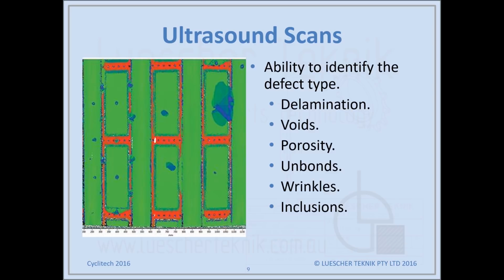The energy is dispersed into the part. So we can tell the thickness, the type of damage, whether it's a delamination or a void, unbond, or a fiber wrinkle or inclusions, etc. We can tell all that from the characteristics of the signal and the trace.